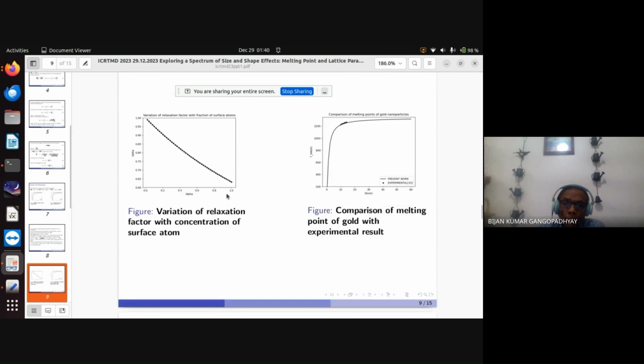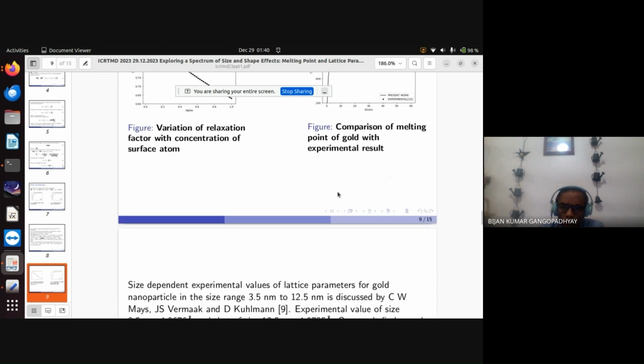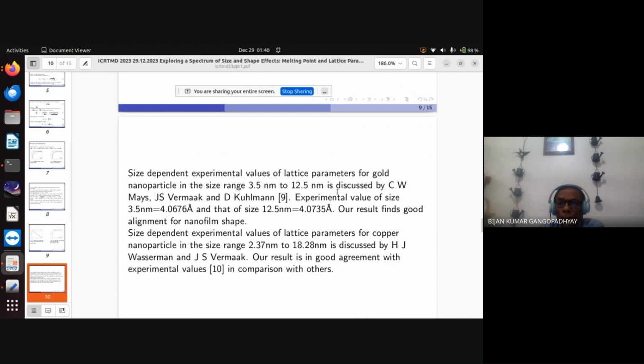So this is the plot between delta, that is the Lindemann constant or relaxation factor alpha, and the experimental values. This solid line is our work, and this dotted line is the experimental value. So our result is within range. For the next parameter calculation, we have considered experimental values. For gold, experimental value for size 3.5, 4.076 for 12.5, something like that. So our result finds good agreement. For nanofilm, there is a question.